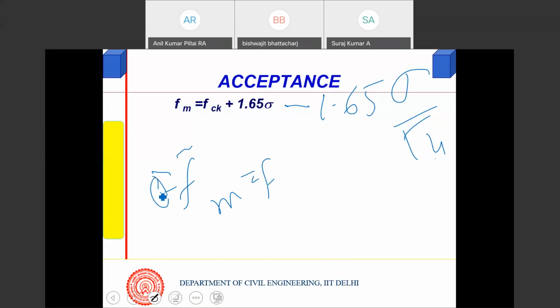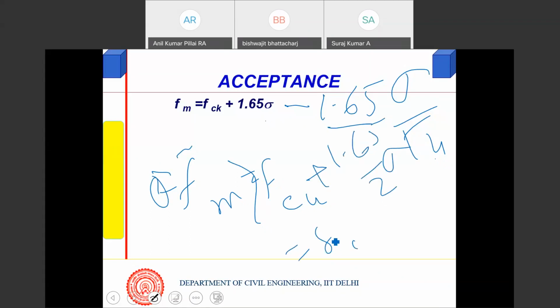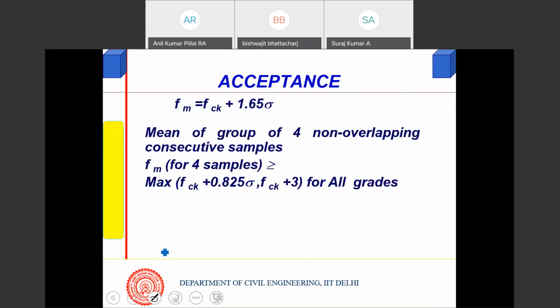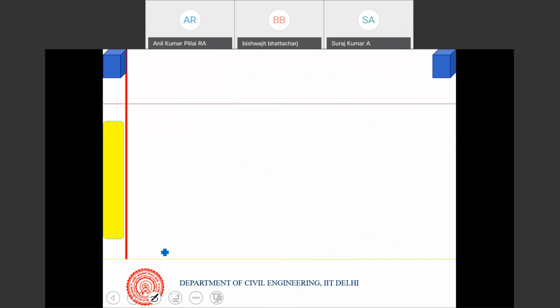The minimum mean you should get, the mean that you are getting, should be greater than FCK plus 1.65 sigma by 2, which is FCK plus 0.825 sigma, for 4 samples. It comes like this. For all grades, they are put in this manner.